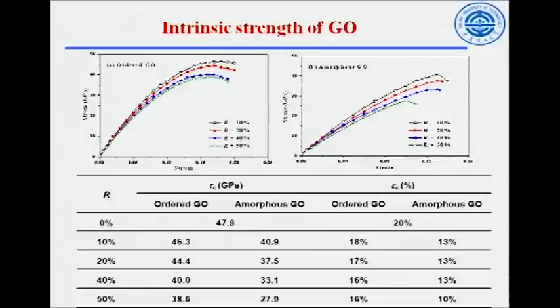And if we compare the ordered structure and amorphous structure, in both cases the ordered structures are stronger due to the higher thermodynamic stability, both in Young's modulus and in the intrinsic strength.